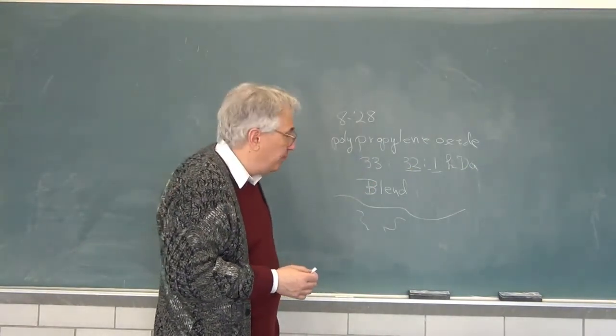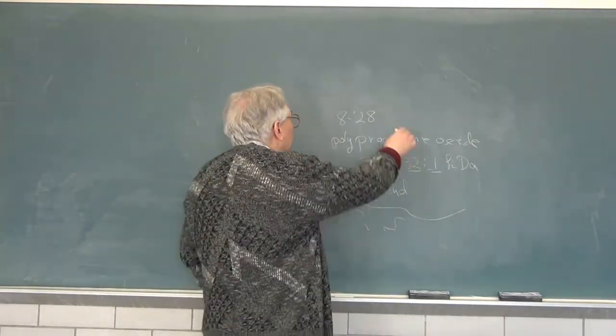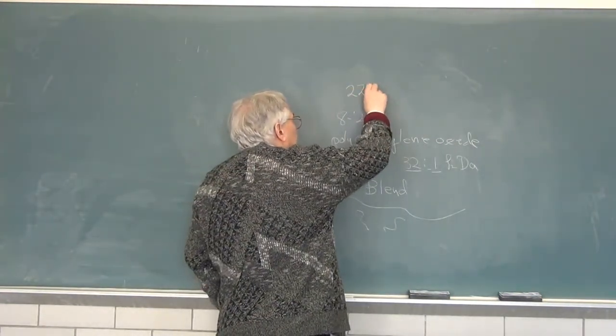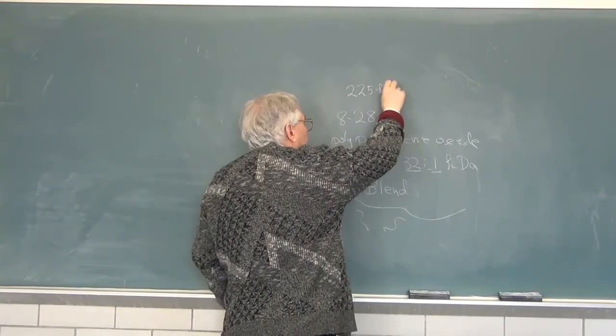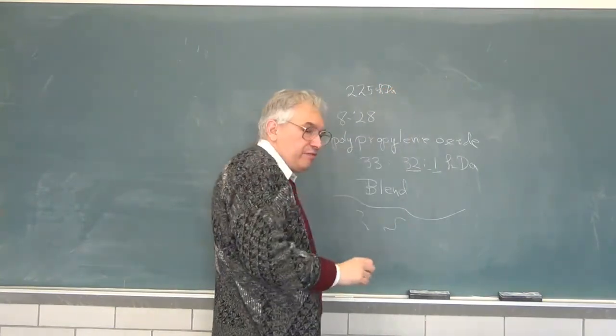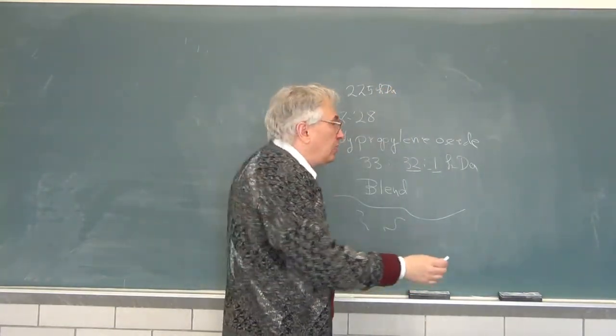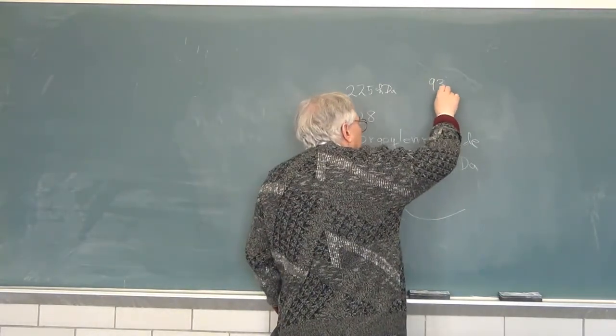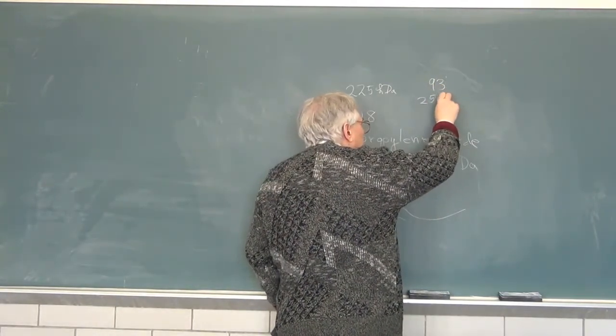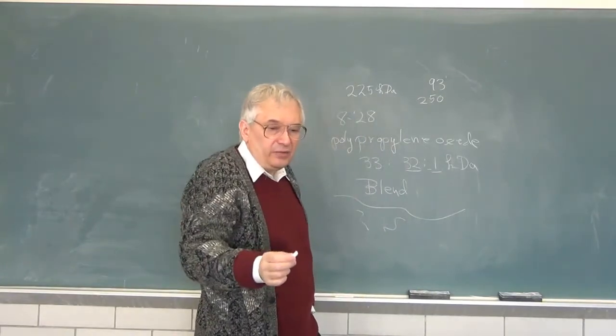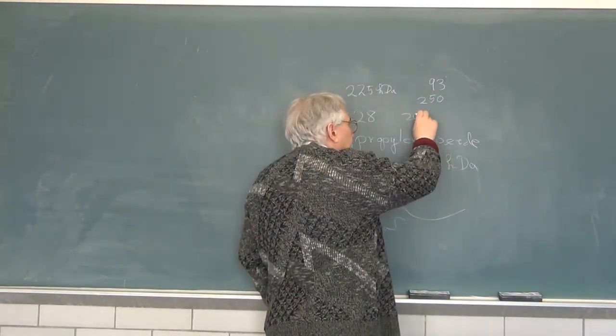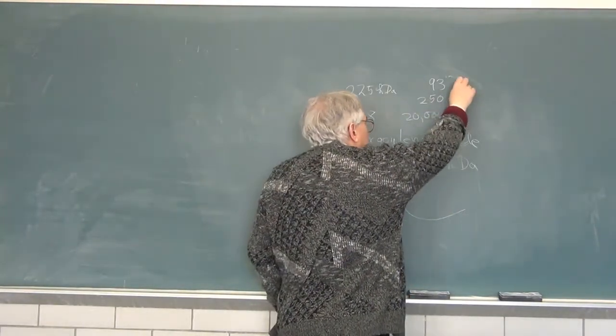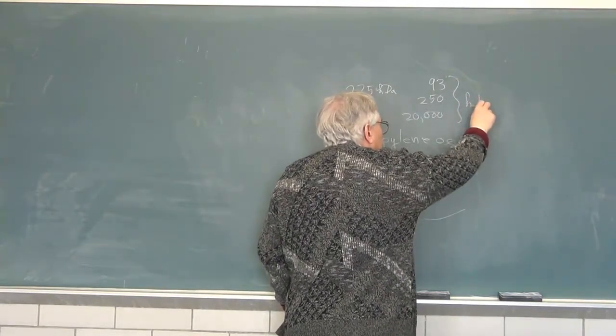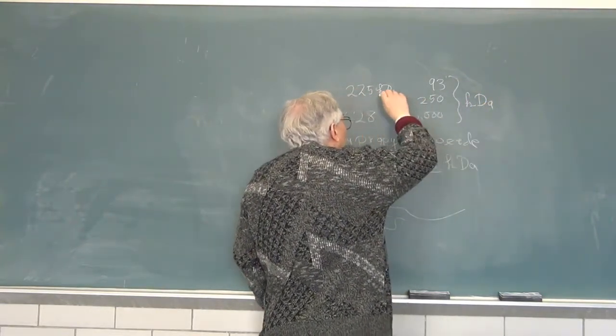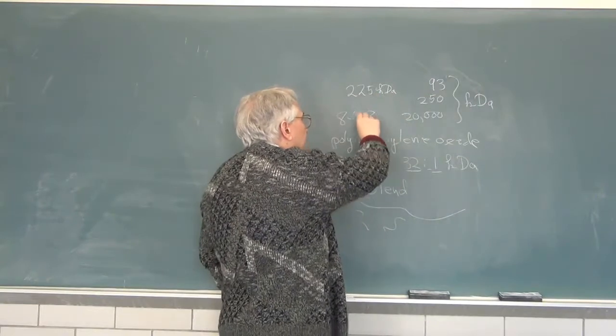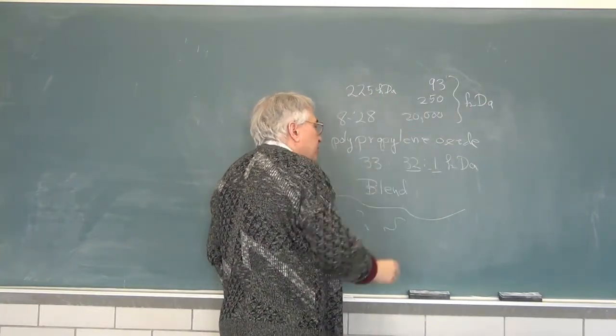Ditto the other groups of measurements, you have a 225 kilodalton probe. You have matrix polymers, which are molecular weights 93, 250, and something really large, 20,000 kilodalton, that is 20 megadalton polymer, and you measure the diffusion of the probes through the matrix polymers.